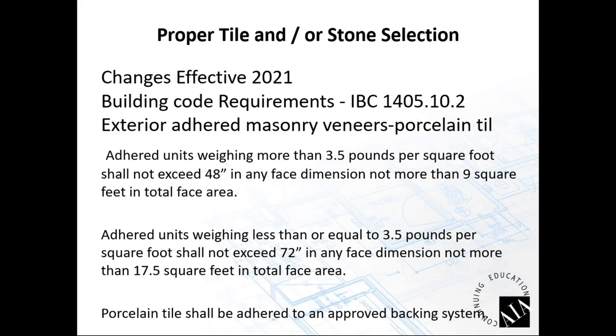And again, what we're seeing now is that an adhered unit weighing more than 3.5 pounds per square foot shall not exceed 48 inches in any facial dimension, or more than 9 square feet total. However, adhered units weighing less than 3.5 pounds per square foot shall not exceed 72 inches in any facial dimension, or exceed 17.5 square feet. What we're looking at, folks, is that these large panels that we're seeing produced, we can now go with a panel 4 foot by 4 foot direct bond, as long as it's a thin material. It's a great step forward when we're looking at adhering systems directly to a veneer.